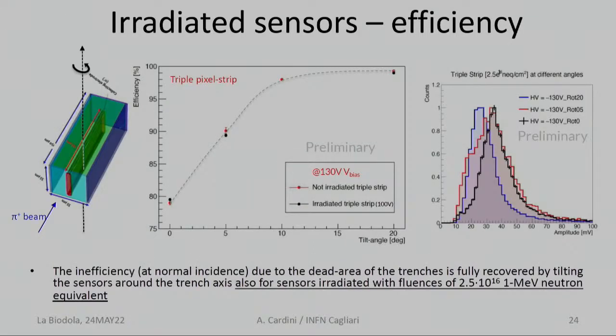The efficiency is practically the same for the irradiated strip supplied at 100 volts and the non-irradiated strip — they are practically indistinguishable, so there is no effect practically. Those detectors are still efficient after this huge fluence.